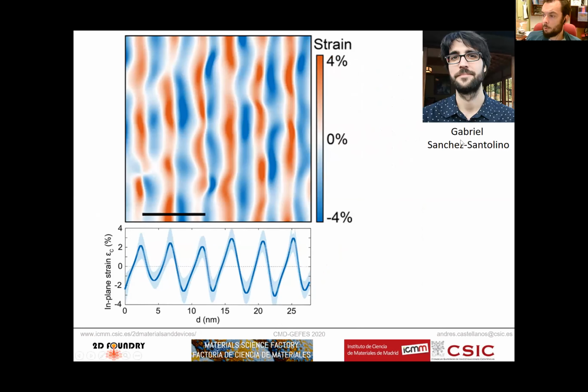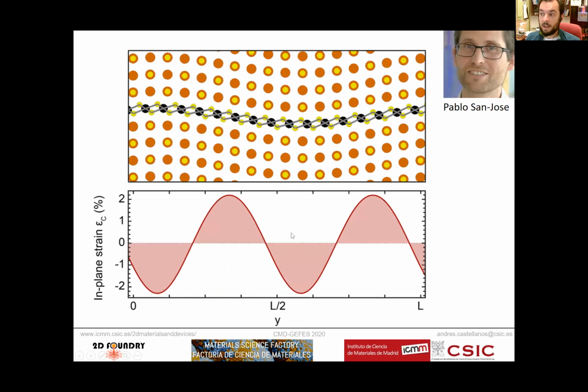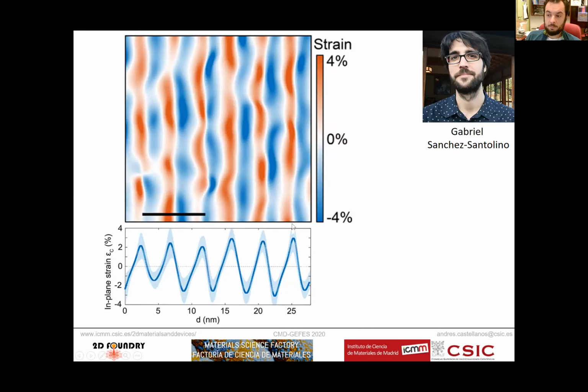Interestingly, our colleague Gabriel Sanchez-Santolino, by analyzing these TEM images very carefully, could extract the position of the atoms in plane and actually map the strain in plane that these lattices are feeling, making a map of strain that matches very, very well with the strain profiles calculated by our colleague Pablo San Jose. Therefore, these systems really have this spatially varying strain profile in order to reduce their energy.